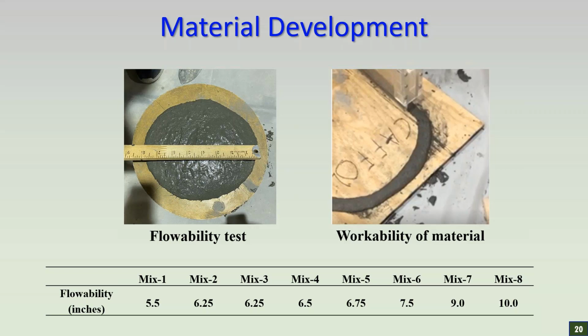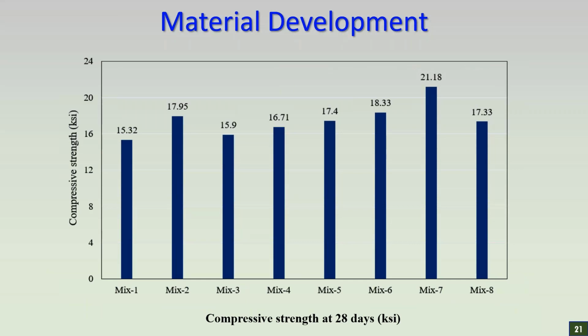Here, two main properties were observed. One is the flowability, and the other is the workability of the material in terms of 3D printing application. An important criterion for ultra high performance concrete is the mechanical properties. The compressive strength of all these mixes was evaluated by performing 28 day tests on the cylinders. It can be seen that mix 7 yielded a maximum compressive strength of 21.18 KSI, but the flowability was 9 inches, which was not suitable for the 3D printing application. Mix 6 showed a good combination of both high compressive strength, more than 18 KSI, and a low flowability, approximately 7.5 inches. So we used mix 6 for the 3D printing application.